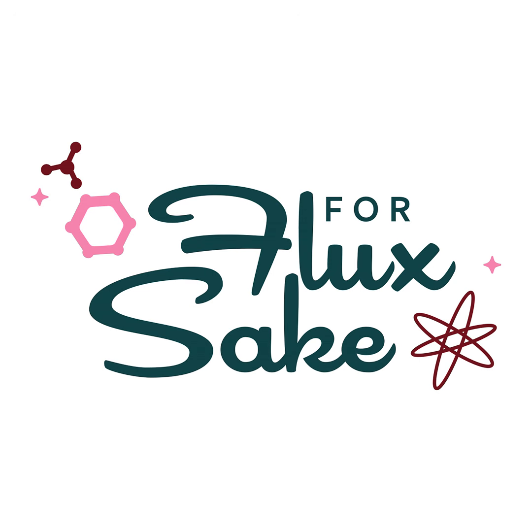Yep. I know. The answer is no. There is no benefit, Teresa, to pushing it to cone 10. Yes, I am a huge fan of cone 10, but it is about the vitrification. The real thing about cone 10 is that it is the most straightforward way to get the best results for vitrification. If you know your chemistry and the clay companies are dialing everything in appropriately, you can pretty much get anything to vitrify at cone 10. It's also the temperature at which you can make the simplest glazes and clay bodies, meaning the fewest number of total ingredients, and still get it to vitrify.